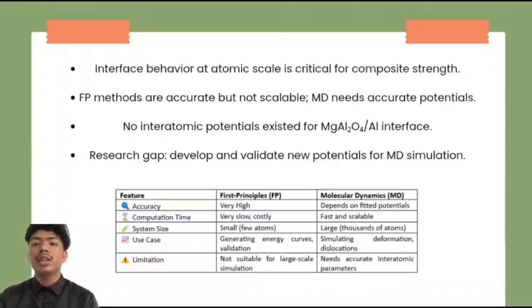Studying this interaction requires molecular dynamics simulations, which can handle large atomic systems and simulate deformation behavior. But MD simulations depend heavily on accurate interatomic potentials, mathematical models that describe how atoms interact. Without these, any simulation results will be unreliable. While first principle DFT-based methods can produce highly accurate interatomic data, they are too computationally intensive to apply directly in large scale MD simulations. On the other hand, MD is efficient but lacks accuracy unless supported by fitted interatomic potentials.